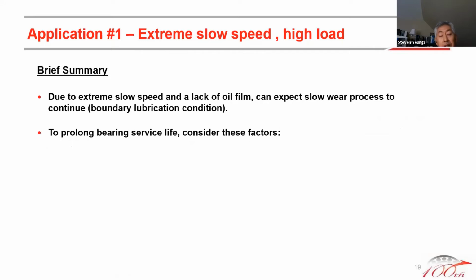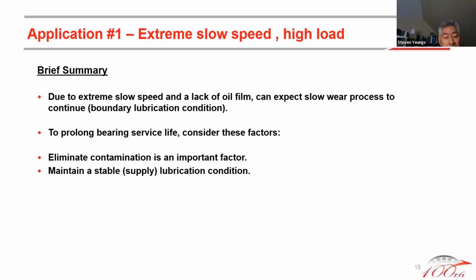And to prolong bearing service life, in this particular application, I would consider these factors. I would try to eliminate contamination, scale, and water on a constant basis. Supply and maintain a constant supply of lubricant to the bearing, even if it's less ideal. Try to use a lubricant with the higher viscosity, which most mills would do, but sometimes they just use a straight low viscosity grease and do not consider the anti-wear additives. And I think that's where the anti-wear additives or EP additives would become beneficial.